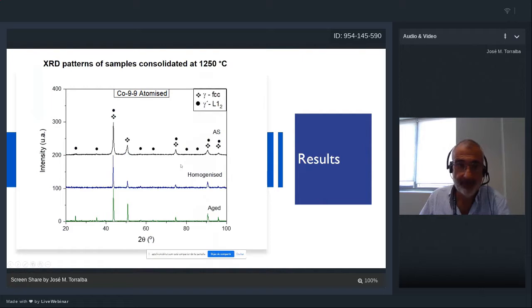So also we have performed the diffraction patterns of the samples consolidated both at 1250 and 1400 in order to get the lattice parameters for the gamma prime and the gamma. But if we see the conventional diffraction patterns, we see that we have very well-defined peaks for the gamma and the gamma prime, but taking into account that both peaks are overlapped, it's difficult in these images to measure the real lattice parameter of the gamma or the gamma prime.